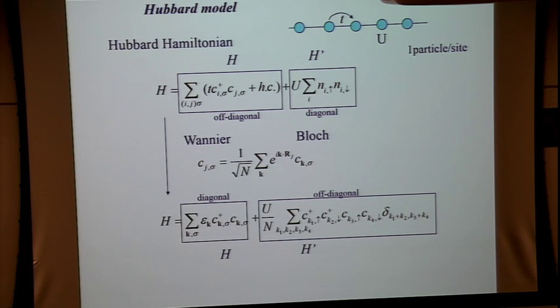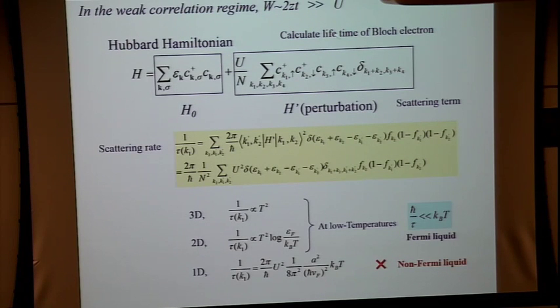For example, in the weak correlation case, the second term is very, very small, so the first term is the unperturbed Hamiltonian. But in this case it's off-diagonal, so you should choose the other representation, because the unperturbed Hamiltonian is diagonalized there. This off-diagonal term is then treated perturbatively, so in this case that term is the perturbation, and the scattering rate is easily calculated like this.